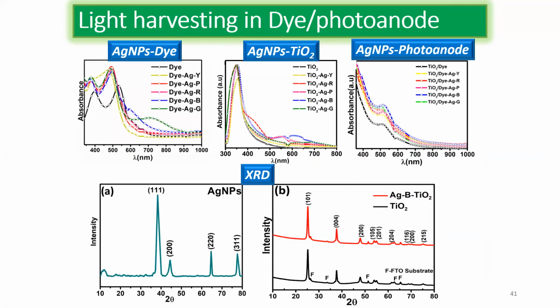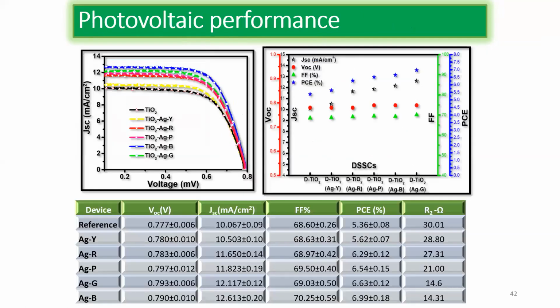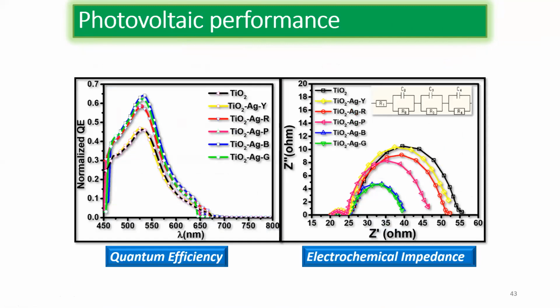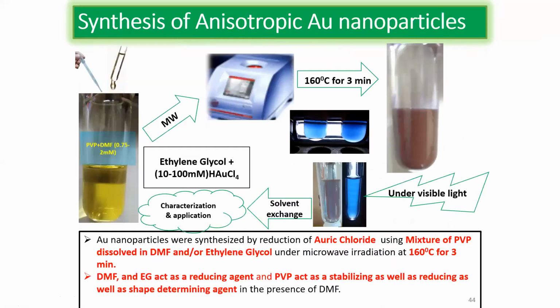These are the same type of characterizations we take: we mix the particle with a dye in the photoanode, and we take the XRD. These are the general characterizations, and it is a must to perform them to check the quality of the material we synthesize. And these are the same IV characteristic data, and we saw how the efficiency improved with time. In this case also I got some 30% enhancement of efficiency. So this is how we perform research and use the plasmonic nanoparticles we synthesize, and overall I got better results with silver.